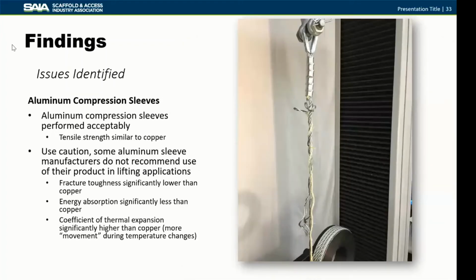So in looking at aluminum compression sleeves, the performance of the aluminum sleeves in our tests showed that they perform as well as copper compression sleeves, and equally as well as a number of the other termination types that we've looked at. But what it doesn't take into account is some of the other issues associated with aluminum as a raw material. And if you look at some of the literature that is published, what you will find is that the fracture toughness of aluminum compared to copper is significantly lower. You will also find that the energy absorption capacity of aluminum is also significantly less than copper.